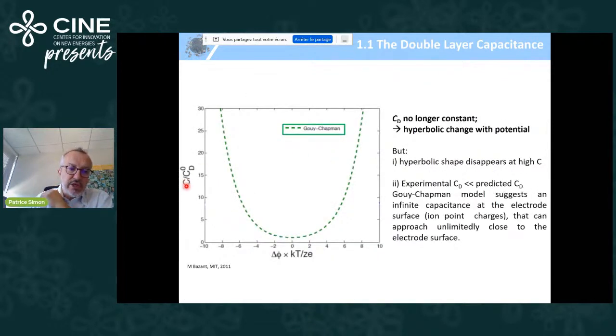So if you plot the change of the capacitance versus the potential, you see a hyperbolic change. But again, you have two different problems. The hyperbolic shape disappears for high concentration electrolytes. And the second point is that all the experimental Gouy-Chapman capacitances were much less than the one predicted by the model. This is because in the Gouy-Chapman model, there is nothing to prevent ions from approaching the electrode surface unlimitedly. So it means that the capacitance at the contact point should be infinite. And this is why this model has some drawbacks.